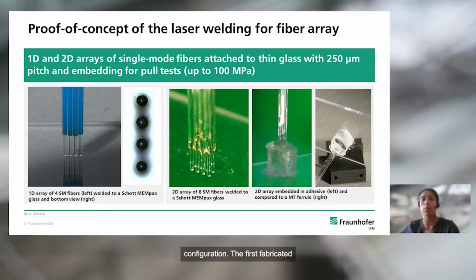The next step is to increase the number of fibers attached on thin glass in 1D and 2D configuration. The first fabricated sample has 4 single-mode fibers with 250 microns pitch. Some issues related to fiber positioning were detected due to tolerance of the acrylate coating of the fibers. This was prevented by removing a few centimeters of coating at the end of the fiber. Light was then coupled through each fiber core. By inspecting the underside of the glass, some artifacts were found due to dust particles on the glass surface. However, a good cleaning process of the glass before welding could solve it.